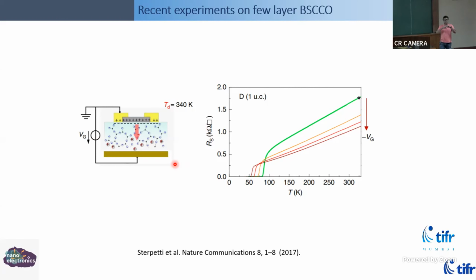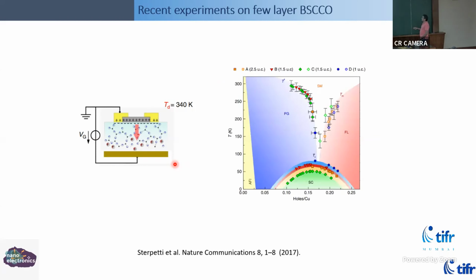You essentially tune the density of charge carriers and you get different transition temperatures. This is the benefit of going down to the 2D limit, because the screening length can be longer in this limit, whereas in the 3D crystal there are a lot of charge carriers, so you can't really apply an external potential to tune the number of charge carriers. And people have actually measured the whole phase diagram using a single device.